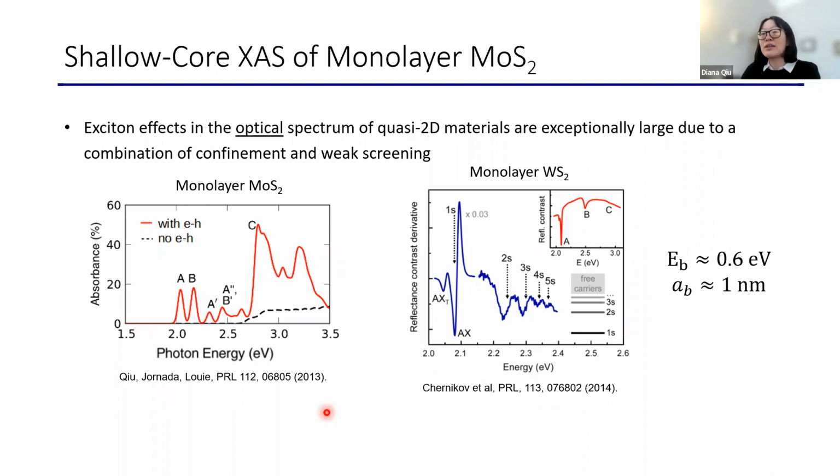There are also dark 2p, 3p, and 3d states, which are dark under single photon absorption. But if you simulate two photon absorption, then you can actually see a bright transition from the 1s-like state to the 2p-like state. And also in experiment, they've been able to do two photon absorption and see transitions to p-like states that are in really good agreement with calculations.